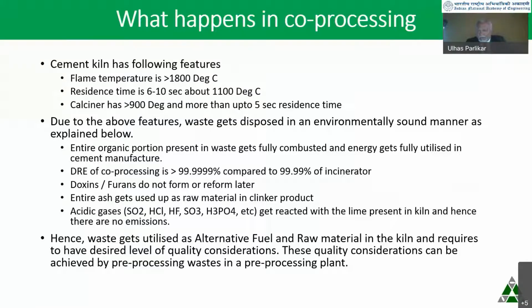So all the acidic gases are taken care of, combustion is taken care of, and because the temperature environment is very high and the gases are cooled in a very particular manner because of the design considerations, there are no possibilities of dioxin and furan formation. All the ash which is present in the waste stream becomes raw material, because ash normally contains only oxides of metals, calcium or magnesium or silicon, iron, aluminum, etc. So it becomes a composite mix for the cement manufacture.